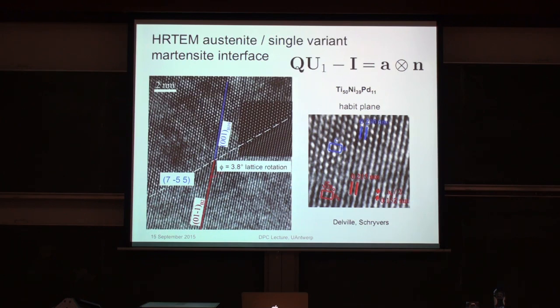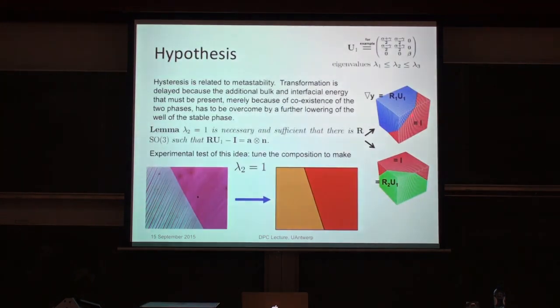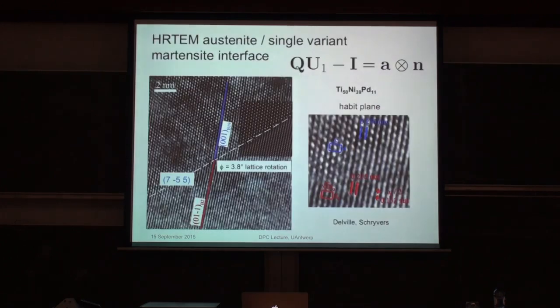And in fact, this was known before the graph I showed you before, anyway, it doesn't matter. So he measured the normal, that's the interface between the two phases. He saw many of those perfect interfaces. And he measured the normal, it turns out that's the N. Don't worry about the formulas, but he measured this lattice rotation, that's the angle in this matrix Q. Anyway, don't worry about details, but the point is that there was a very nice agreement of all the interfaces that he could see, and the interfaces expected when lambda 2 is 1. In other words, theoretically, these were the interfaces he was observing.